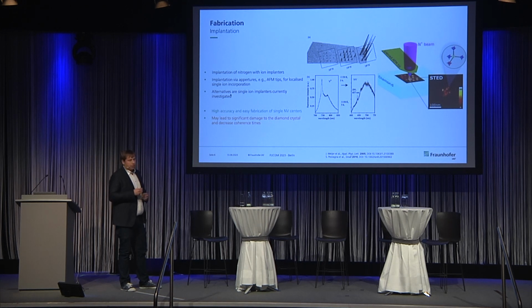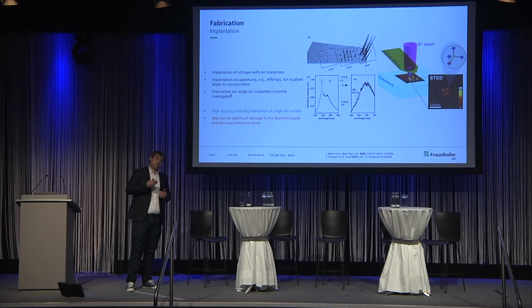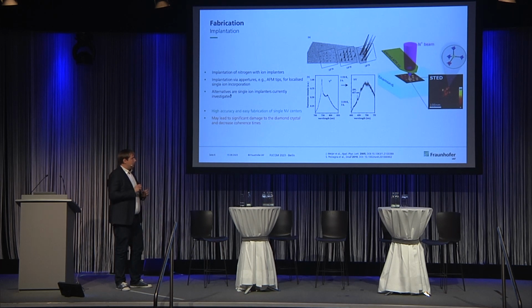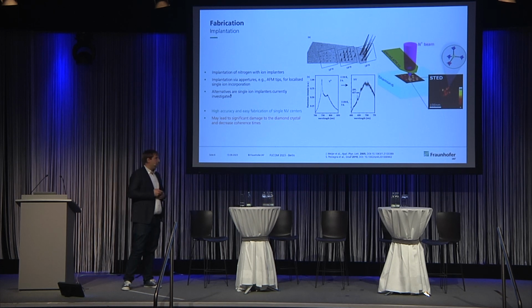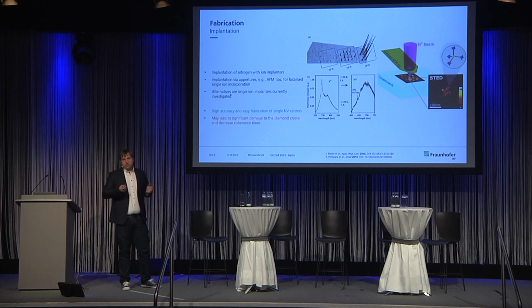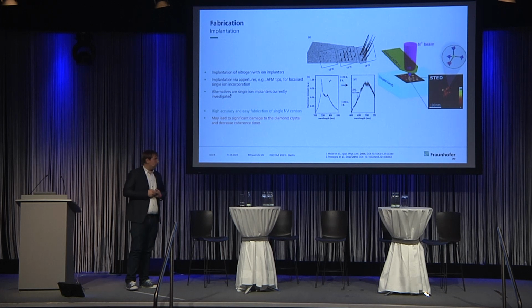There are some means to circumvent these problems, but for diamond there is nothing that you can do, like for example a thermal treatment, that will heal out all the defects, unfortunately. So you will have to live with some of these damages, and these will actually decrease the coherence time. So this is one approach. It's working perfectly to make individual NV centers, but at the cost of a bit of coherence time.